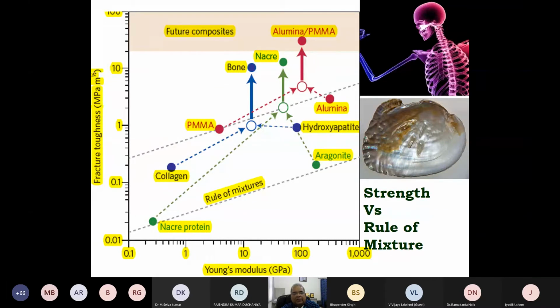It's a nanocomposite of the protein called collagen and mineral hydroxyapatite. This is one of the calcium phosphate family members. The collagen is a matrix, and in that matrix is mineralized by hydroxyapatite nanoparticles. If you look at the fracture toughness of the collagen, it is just above 0.1 MPa under root m, and hydroxyapatite is somewhere around 1 MPa under root m. But if you put them together, then defying any law of mixture, the bone has a strength at least more than an order of magnitude higher than that of the hydroxyapatite.